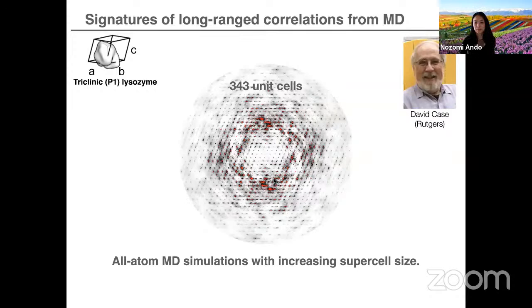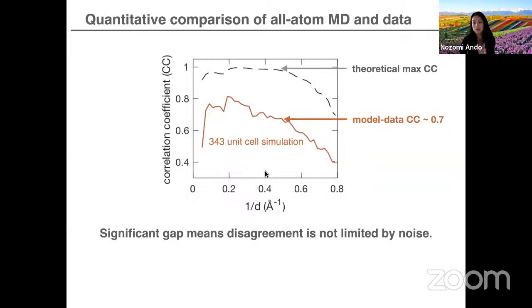Unfortunately, even though those simulations were really state of the art and probably the largest simulation that had been done of a protein crystal, we were still far from the theoretical maximum agreement that we could get with the data. So here I'm showing the correlation coefficient as a function of resolution or inverse resolution, and our data quality was extremely good. And so the theoretical maximum was very high as well. But the best MD simulation still maxed out at roughly 0.7.